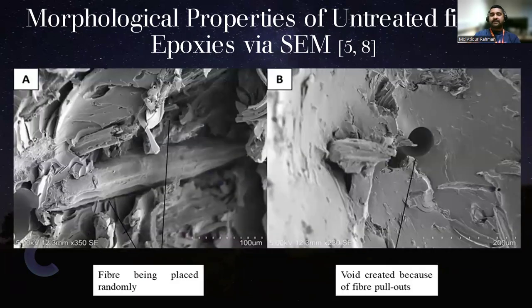Let's see the results. First, morphological properties, untreated epoxy via SEM. This is the fracture surface of the untreated fiber reinforced epoxy composite. When you see that under the microscope, we have found that the fiber is placed randomly rather than in a very orderly manner. And after the fracture, there is void creation. These are indications of poor adhesion, and that happens because earlier we have seen that the untreated fiber is filled with all those pectin debris. That's one of the main reasons.